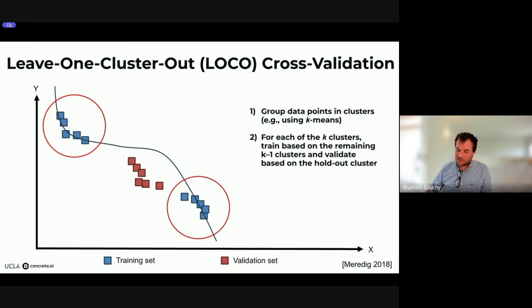Once we have grouped the data points into clusters, what we do is that, rather than doing a random train validation split, we take all of those clusters one by one, and then we do a cross-validation where we isolate one cluster that's going to become the validation set, and all the other clusters are going to be the training set. And we do that in a cross-validation way by using all of those clusters as a distinct validation set. And then we adjust the hyperparameters of the model to reduce the validation error as much as possible, right? So we still keep the same idea of cross-validation, but we do it cluster by cluster rather than with a random train validation split.